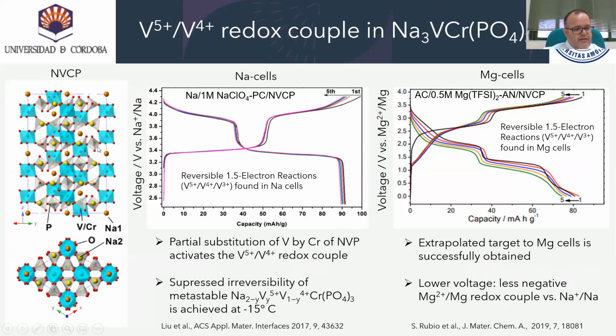In the NVCP crystal structure, the octahedral VO6 interlinks via the corner with tetrahedral PO4 to form the three-dimensional V2(PO4)3 lantern units that are interconnected through PO4 with the neighboring units. 6 lantern units build up the primitive cell of NVCP, in which 2 different oxygen environment interstitial sites exist: sodium 1 with 6-4 coordination and sodium 2 with 8-4 coordination, as we saw before.